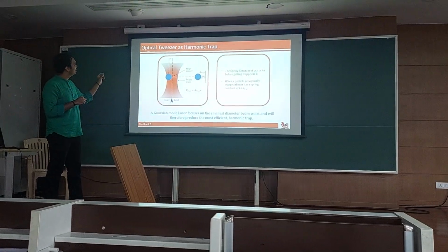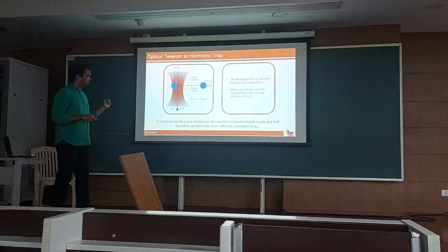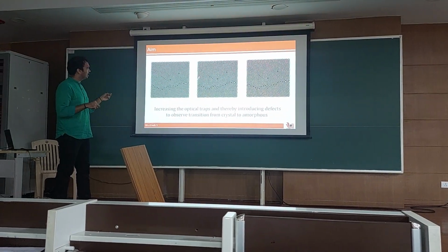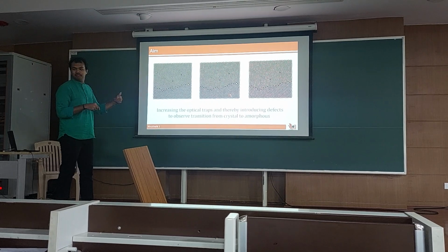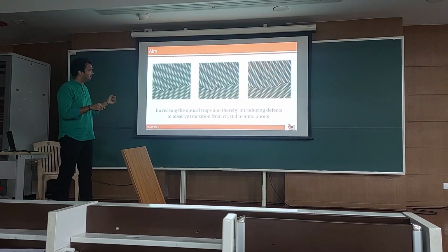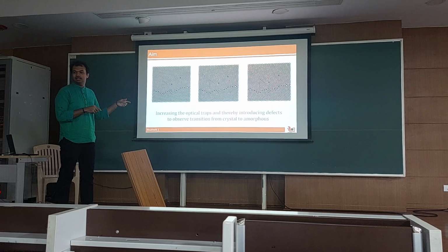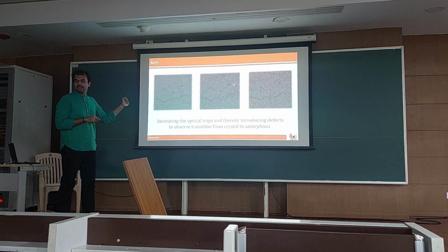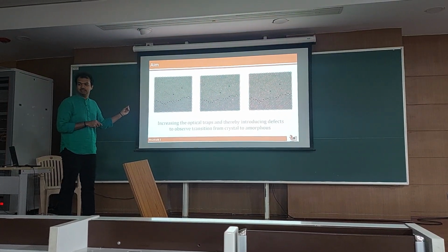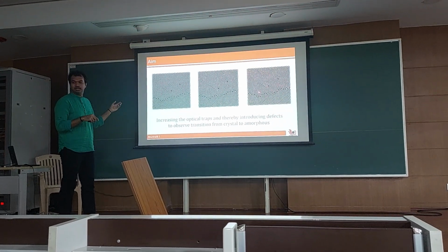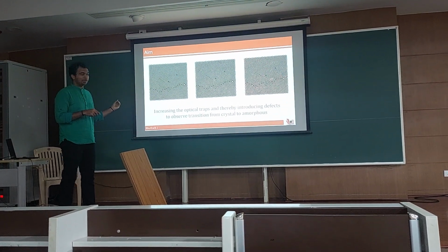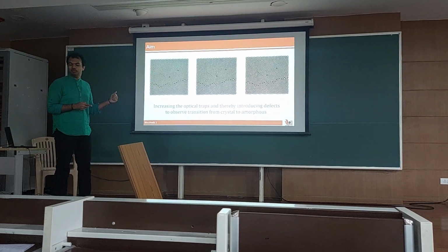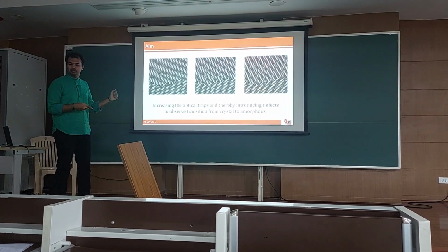We know an optical tweezer is a harmonic trap. So if we randomly pin some of the particles, it introduces defects into the system. These particles will be different from the surrounding ones. Even though structurally they are crystal, in terms of phonon modes they are not similar to the surrounding system. So we will increase the concentration of pinning and see at what percentage it goes from crystal to the amorphous state.